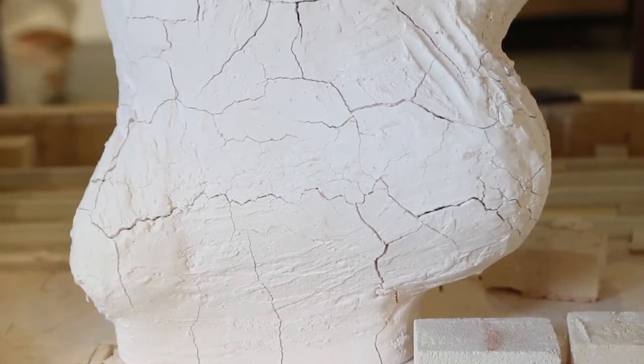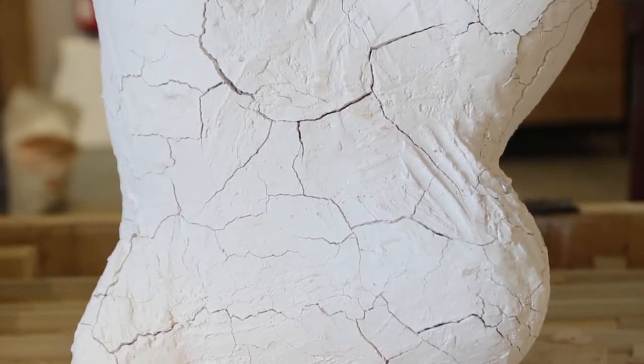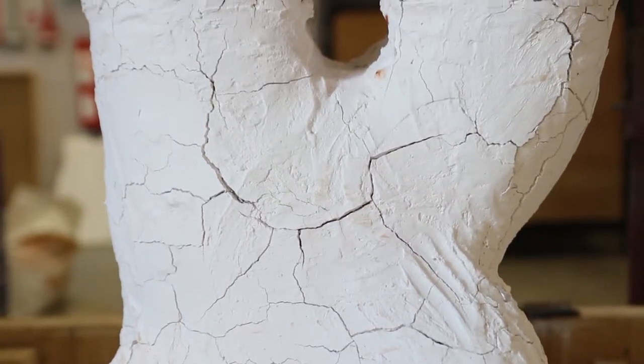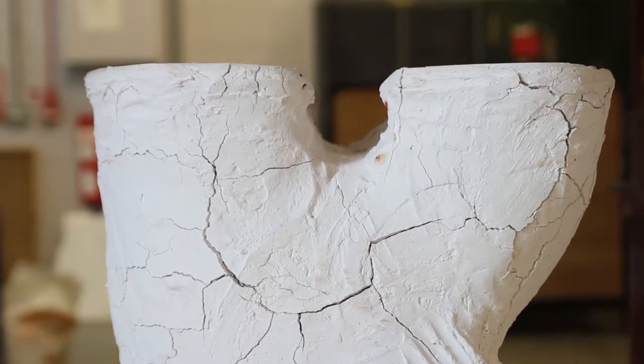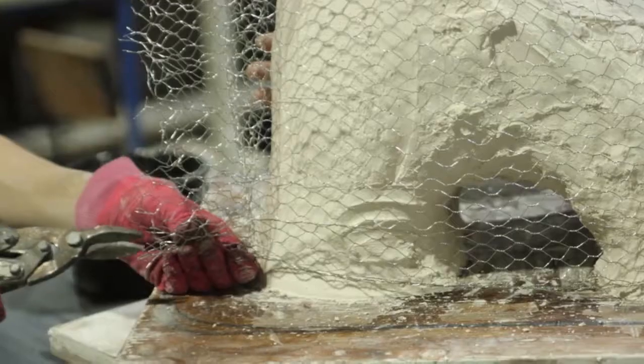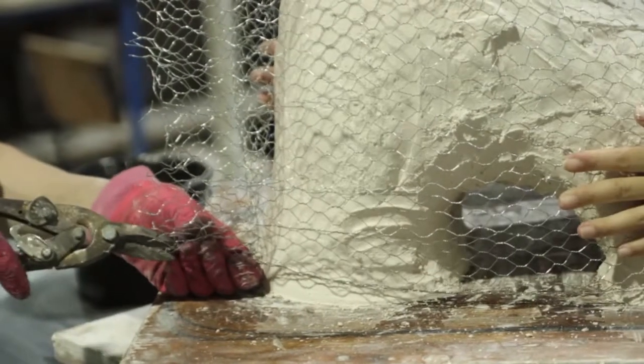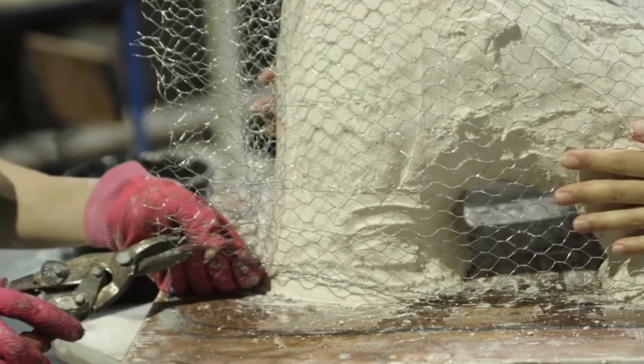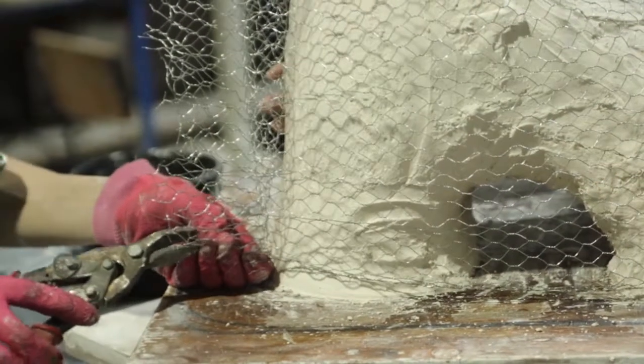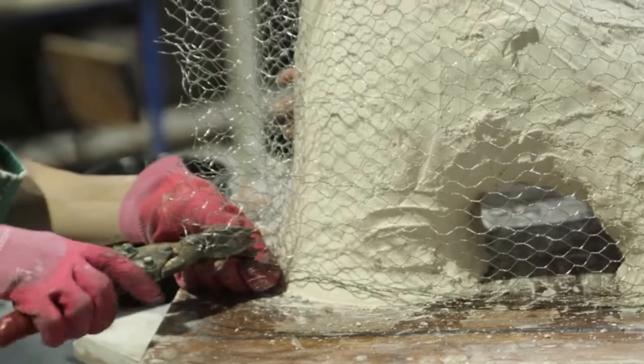Then I start making the refractory mold. The refractory mold is the mold that actually essentially goes into the kiln. It's called refractory because it's designed to sustain extreme heat through a prolonged period of time. The way I make it is just build it layer by layer, and each layer introduce some other reinforcement material that will make the mold as hard as I can make it on the one hand. On the other hand, I want it to be relatively light.